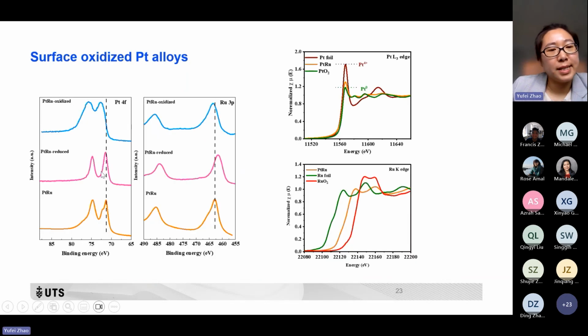We have done the characterization. Here is XPS and XAS. For the XPS, we can see that for platinum and ruthenium, the valence states of these two elements sit between the platinum ruthenium reduced and oxidized samples. And for the XAS here, we can see the XANES result. The platinum sits between the valence state of 0 to 4+. And for the ruthenium, it also sits between the ruthenium foil and ruthenium dioxide.